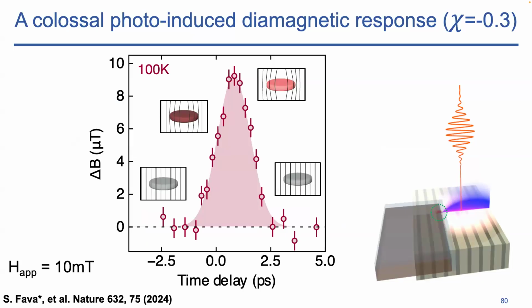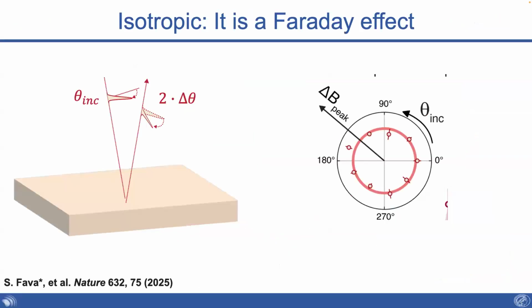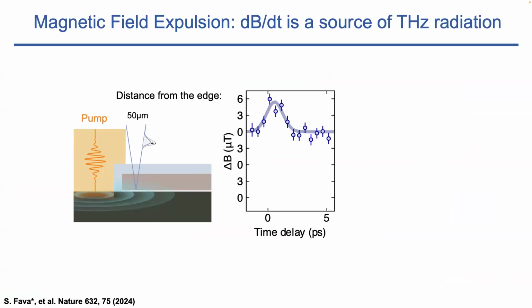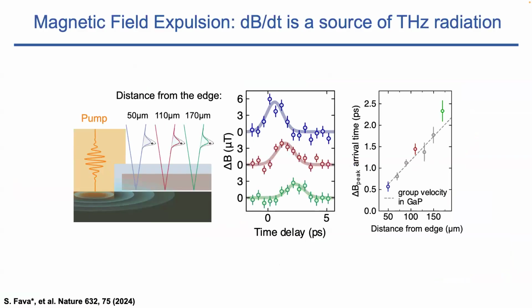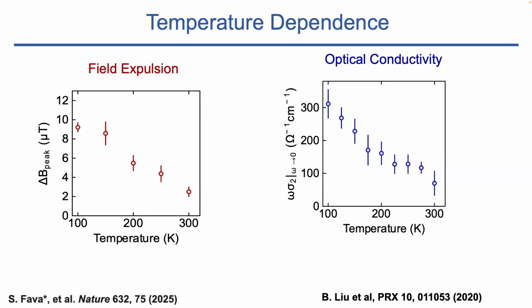Okay. When you go to room temperature, you get this. So chi gets quenched to something like minus 0.05 to minus 0.07. Again, far larger than what a light-induced perfect conductor would look like. There's a number of checks. I won't go into too much detail here, but this thing, if it's a Meissner effect, should be completely independent of the incoming polarization angle. We've also measured, this is not that important. The important thing is that this was the optical conductivity determination up to T star, and this is the magnetic field expulsion that goes all the way up to T star, telling you that these two are approximately the same. We've only looked at this effect in one doping level.